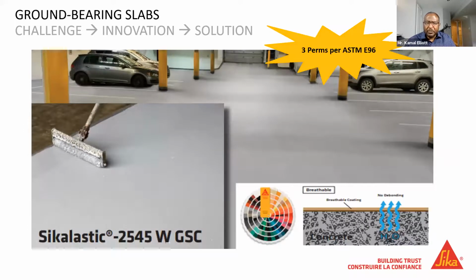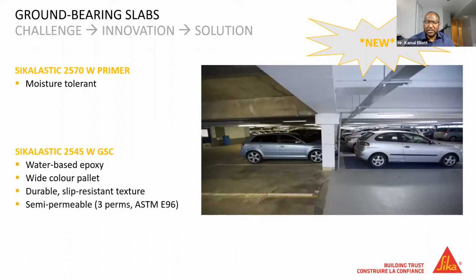So at Sika, we've been able to advance one of our technologies to the point where it's a durable coating. It'll protect the slab. It'll give you that nice opaque uniform finish in pretty much any color in the rainbow, but it will also be breathable. So it'll be tough, colored, and breathable. It'll allow moisture to escape at a rate of 3 perms if there's rising moisture underneath. So it's a somewhat unique solution to a longstanding condition.